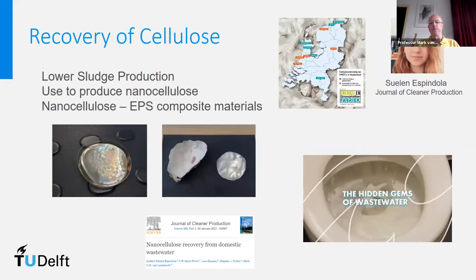Cellulose, I mentioned already. So cellulose is an interesting product to recover because it is a significant fraction. Cellulose in winter temperatures in Northern Europe is not degraded in the treatment plants. In summer times, it is partly degraded, but it ends up in the excess sludge. And it's about 20 to 30% of the excess sludge. We produce per person about 10 kilograms of cellulose or toilet paper per year, which we flush down the toilets.